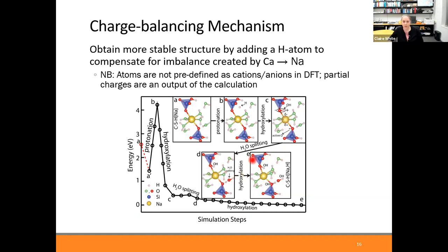And this also, what we found is that it wanted a symmetric charge distribution around the sodium. So we actually ended up with these two hydroxyl units forming, and then there's another hydroxyl floating around in the system. But this ended up with a more symmetric charge distribution around the sodium, which we think is leading to a more stable system overall.